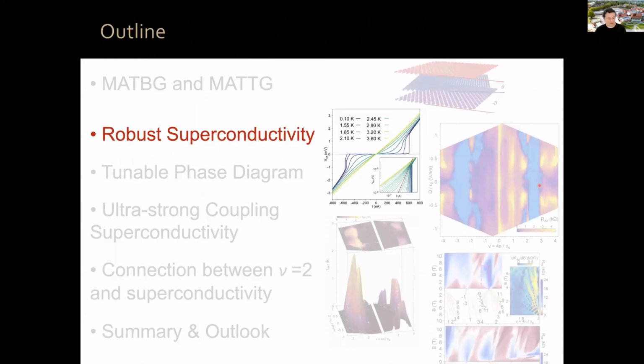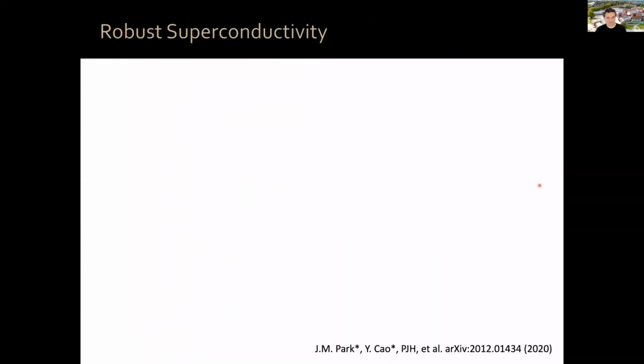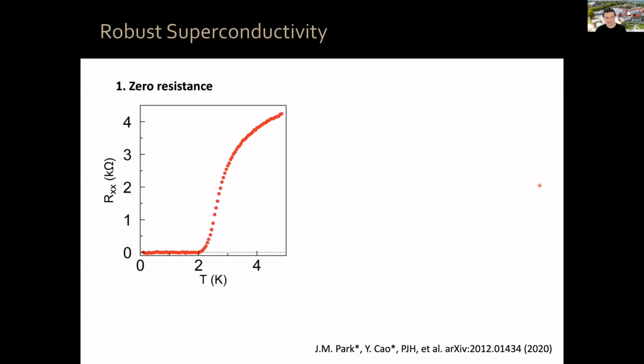Now, let me tell you about robust superconductivity. So as I mentioned earlier, at the beginning of the introduction, if you want to see robust superconductivity, you have to show zero resistance. Here we go. This is the resistance of one of our magic angle twisted trilayer graphene devices. Now, this is a fit to the Halperin-Nelson formula, Nelson-Halperin formula, for T_BKT that can be obtained. You know, T_BKT is about 2.3 Kelvin. T_C at 50% normal state resistance, about 2.9 Kelvin.